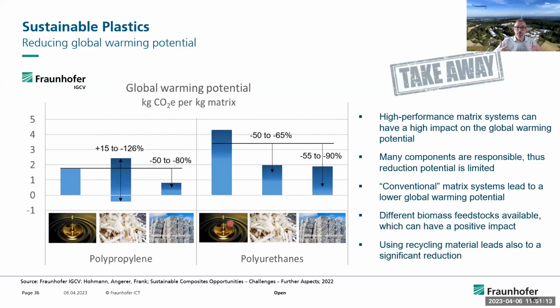but we have to really utilize all the potentials in order to derive chemical building blocks from natural sources and return them into the loop, using them in a circular manner to get to that high savings. The fluctuation is somewhat higher for polyurethanes, because polyurethanes consist of two polymer components, polyols and isocyanates. For both, bio-based versions are already commercially available, and recycled polyols are also under investigation. So depending on the combination of these components, the reduction potential can be up to 90%.